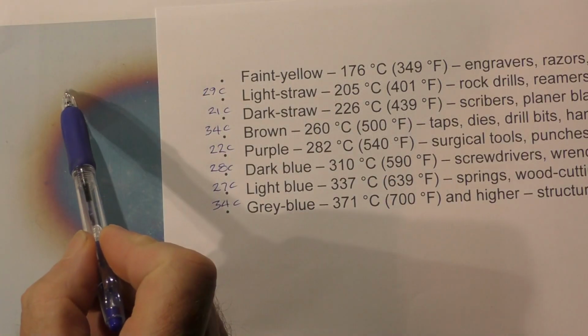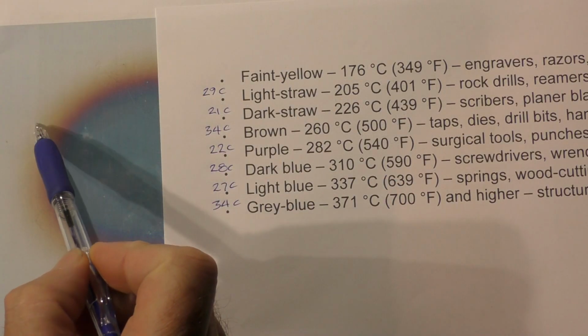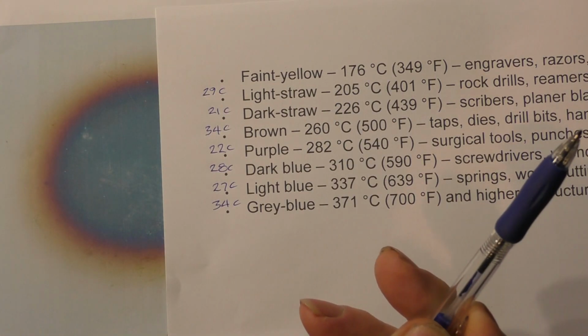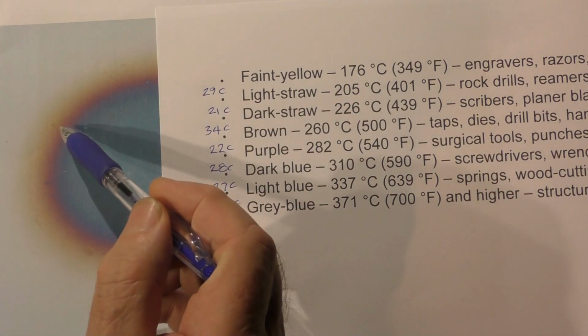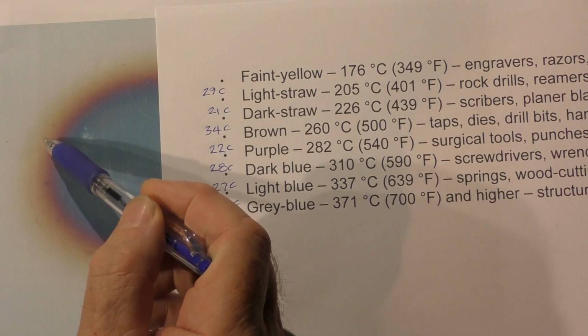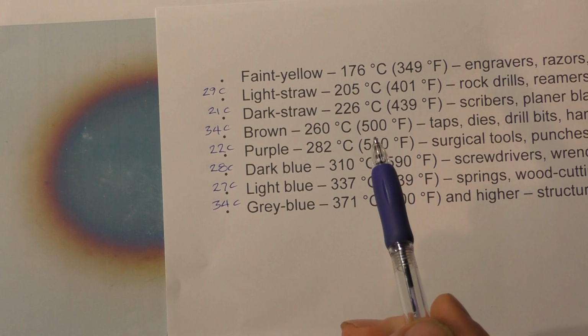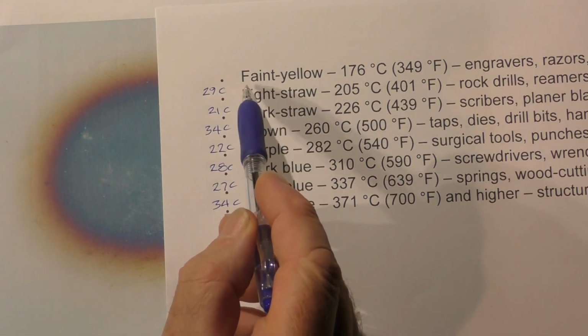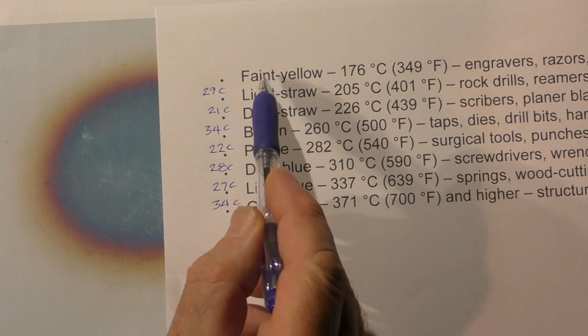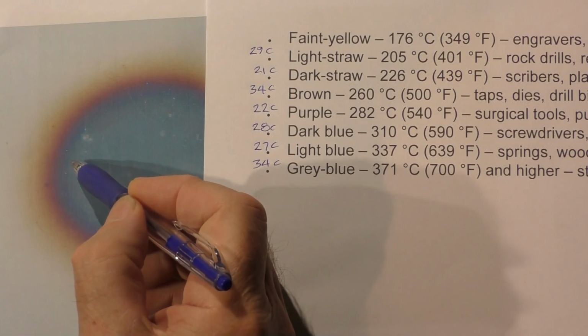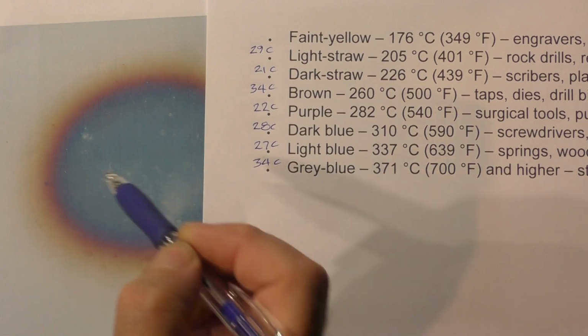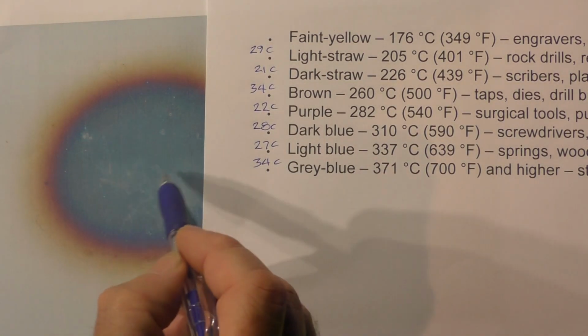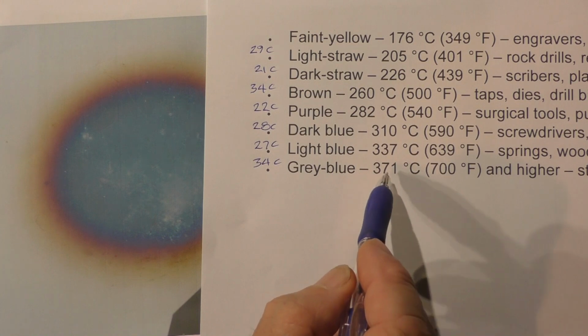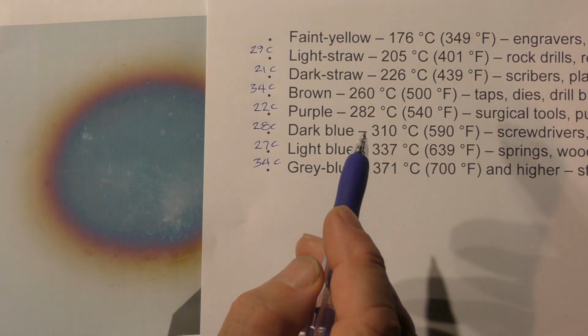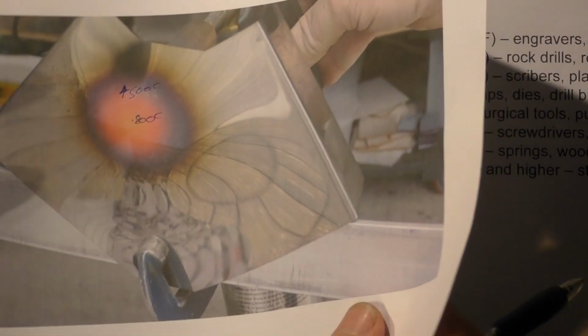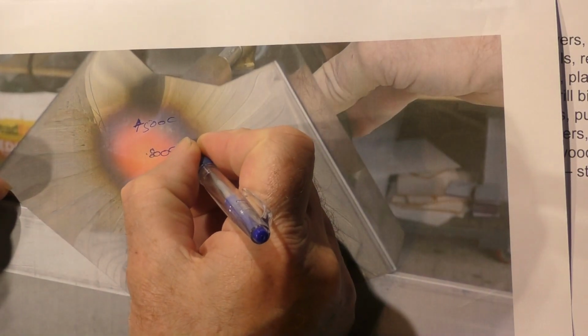So for instance, the outside edge there, called faint yellow, which is right out here, 176 degrees C. Light straw, which is this secondary phase in here, 205 degrees C. It's only 29 degrees C hotter, but it changes from faint yellow to light straw. And then we've got this area here which is classed as light blue, and then all this section in the middle here is classed as grey blue, and we're talking about 371 degrees C. So let's just put that on the chart there, that somewhere around about there,